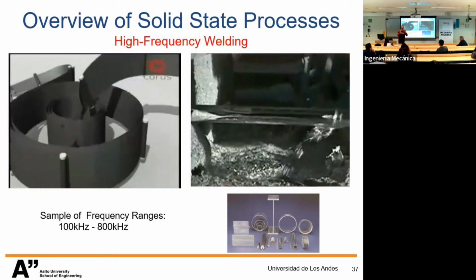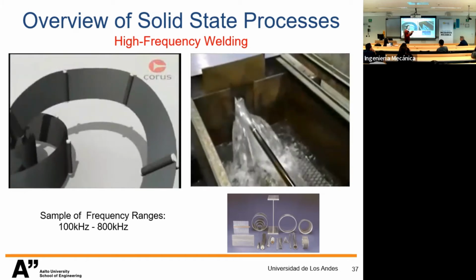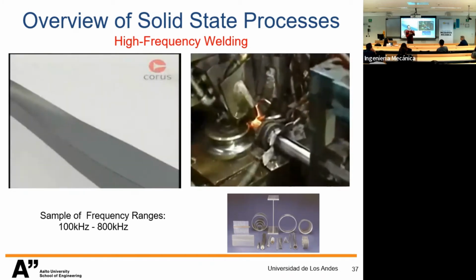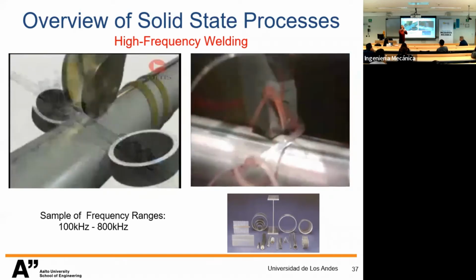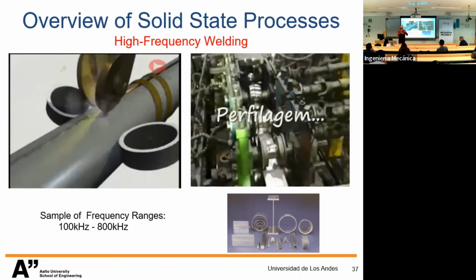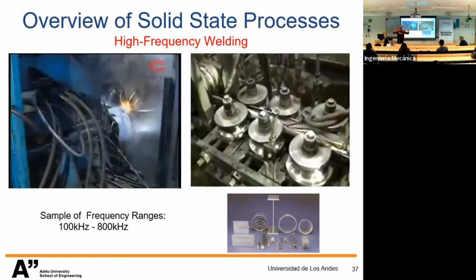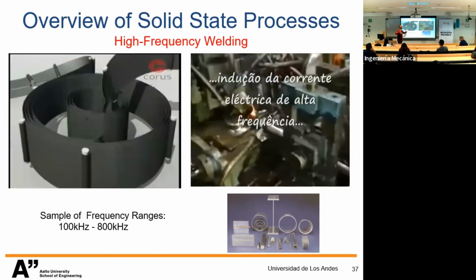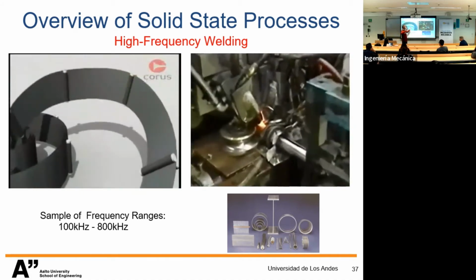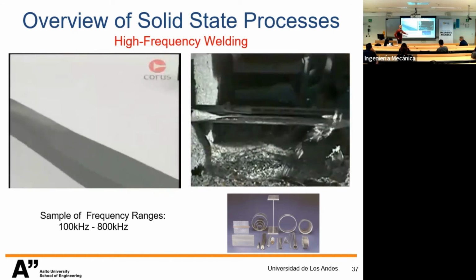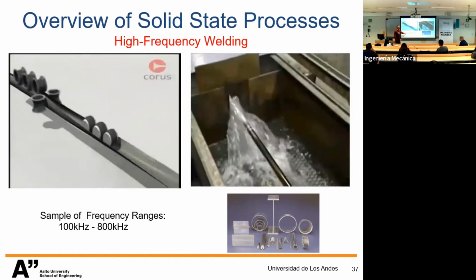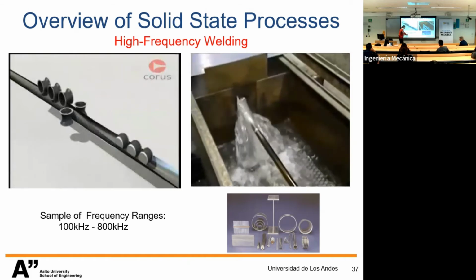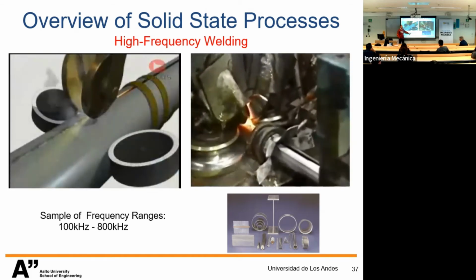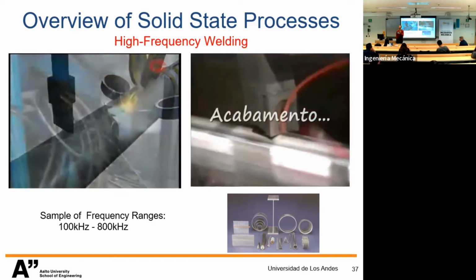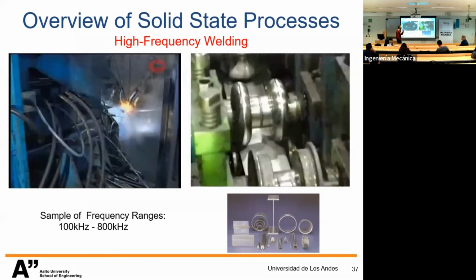So in DC current, direct current, okay, you have the flow of energy flowing uniformly through the component. In AC, it starts to get closer to the surface. Okay, and as you increase the frequency of AC current, you increase the skin effect. And if the frequency is very high, so you know what is the frequency in our network typically? So 60. Yeah, 60. So you see that we are now speaking of 100,000 to 800,000. So the skin effect is very high. You have liquidification of the surface.